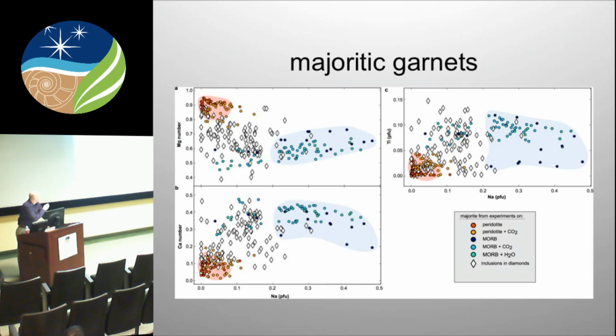And again, we crystallize titanium-rich calcium perovskites. We crystallize majorite garnets that have the same sodium contents, and we crystallize ferropericlase, and we crystallize diamonds in these experiments. Tyler, you have a question?